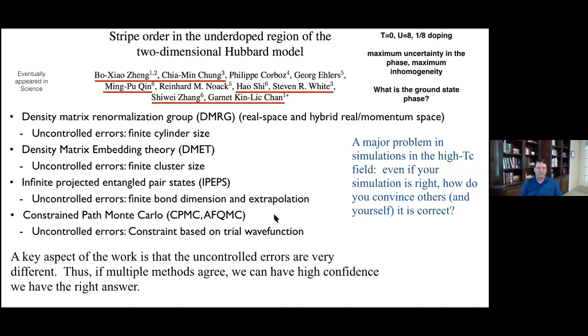This type of Monte Carlo has a constraint on the trial, on the motion, the Monte Carlo evolution. It's an uncontrolled error what this constraint does, but it turns out to work very well. But it has to be checked with other methods where we understand the errors better. So a key aspect of this work is that the uncontrolled errors in these cases are very different. And so if you have multiple methods agree, then you can have much more confidence in getting the right answer.